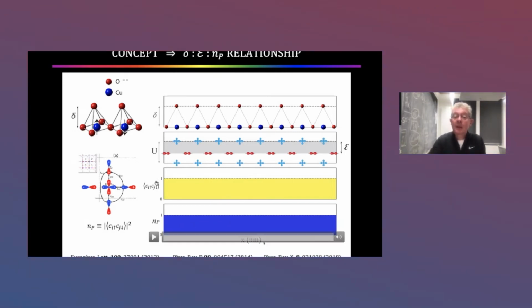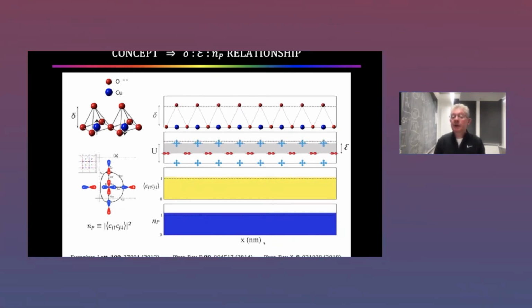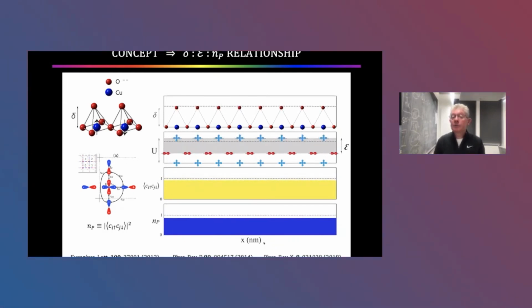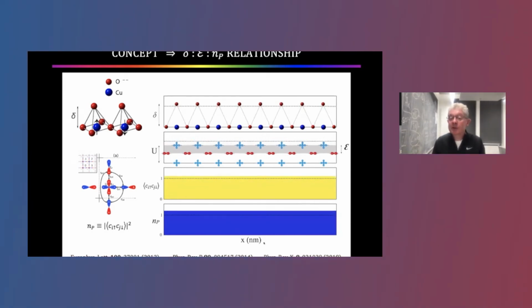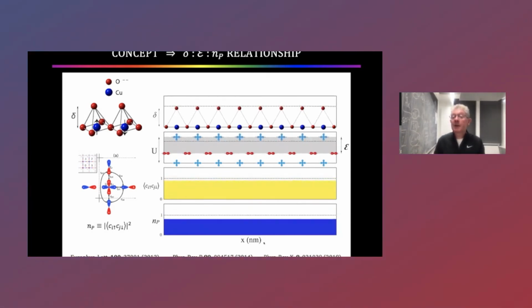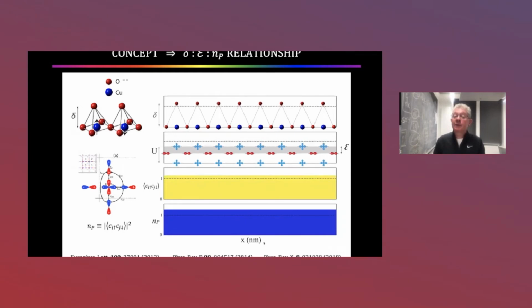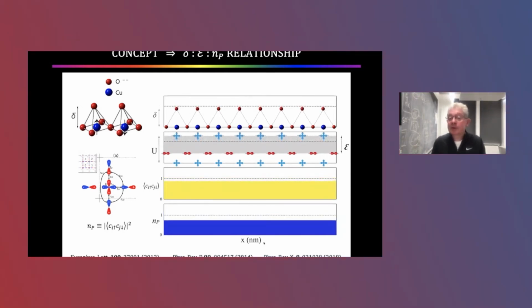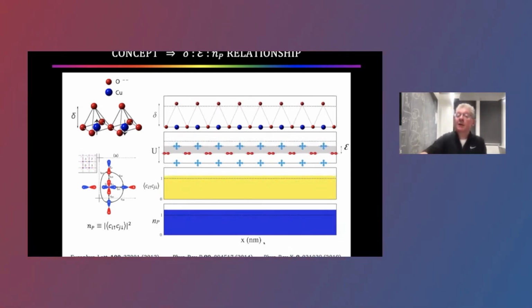So if we could change the apical distance, what would happen to the charge transfer energy epsilon, and what would happen to the electron pair density? Well, as a cartoon, this is what we would expect. As we move the apical away, the charge transfer energy goes down, but superfluid density goes up. As we move the apical towards, charge transfer energy goes up, but superfluid density goes down. That's the concept.